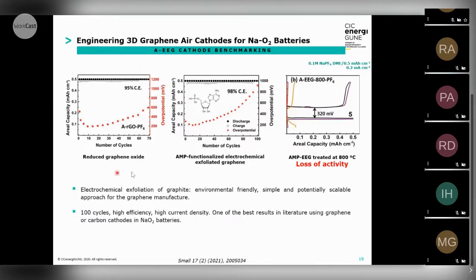Here you have the cyclability of reduced graphene oxide, where you have a 95% Coulombic efficiency, and you can see an increase in the charge overpotential of up to 300 millivolts when you cycle the battery for 70 cycles.